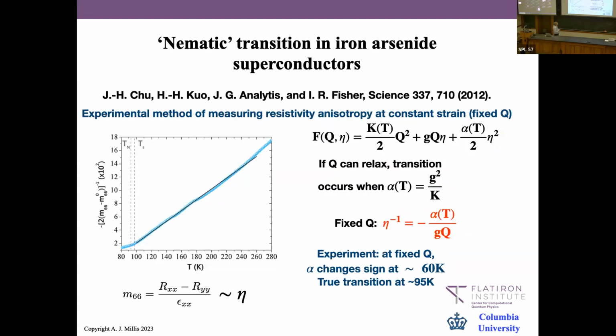All right, so what Ian and his collaborators did - this is the paper - was find a clever way of measuring electronic properties at a fixed value of the lattice coordinates. What they did was fix strain, or vary strain over a small range, and they measured the anisotropy in the electrical resistance.